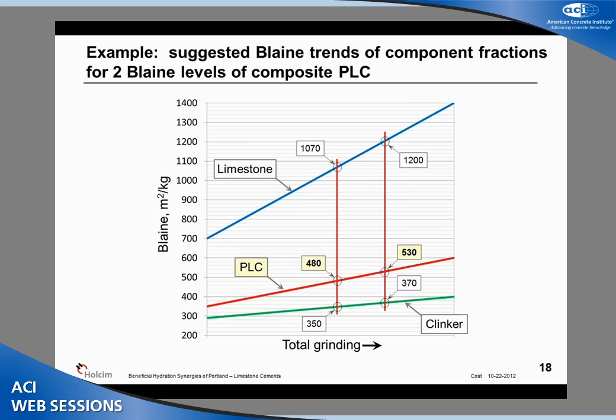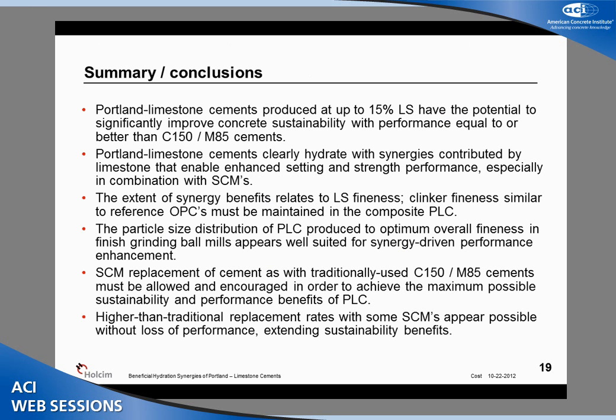As the Blaine of the PLC increases, the Blaine of the clinker is increasing very slowly, but the Blaine of the limestone is increasing much more rapidly. Here would be an example of about 100 square meters per kilogram higher than the ordinary Portland cement Blaine. If you only go up another 50 points, the additional limestone fineness is significant, but for the additional clinker fineness, we're probably not even back to the original OPC fineness of the clinker particles yet. That's our premise anyway. That's where we think we are with this.